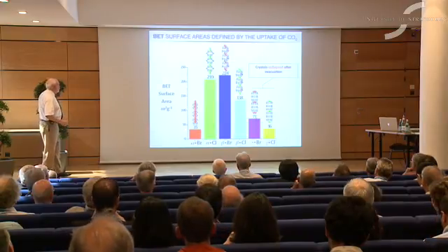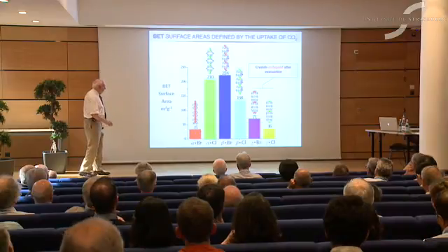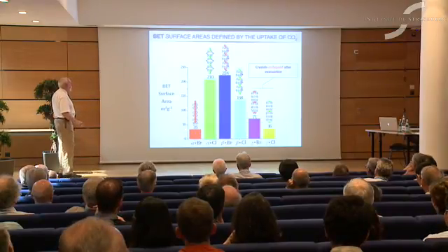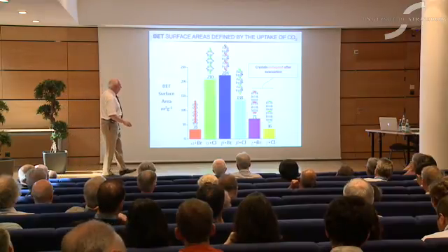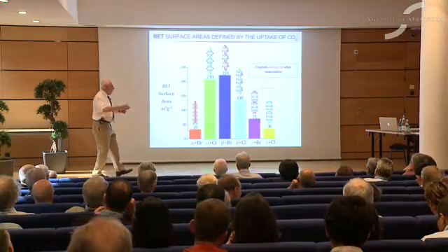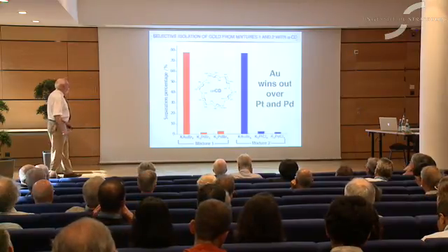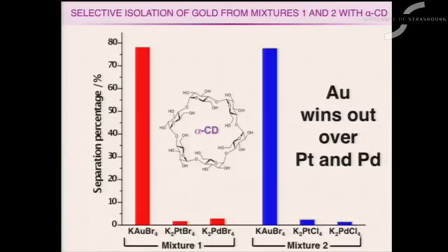And if you do some BET surface measurements, of course, it tells you that, well, there's not much space in here to park anything, whereas there begins to be a lot of space in these ones. And then when those ones have not even got the potassium ions to hold together, they just collapse during the experiment here. And it's hugely selective. It's gold, and it's gold alone.